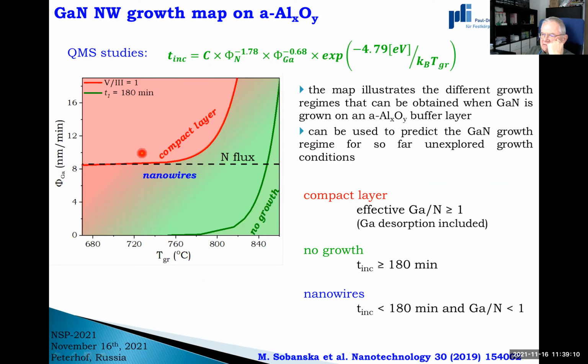The first boundary is right here. What does no growth mean? We have decided that if incubation time is longer than 3 hours, then the growth is useless, impractical. So we put 180 minutes here, and this allows us to draw this line. This is the regime where there's no growth of gallium nitride at all.